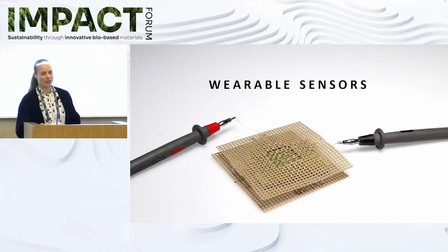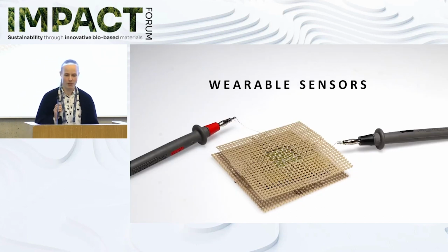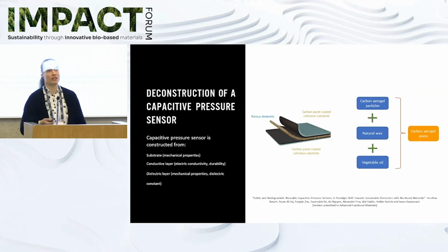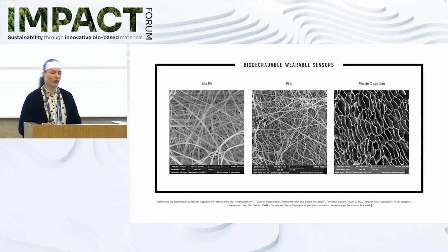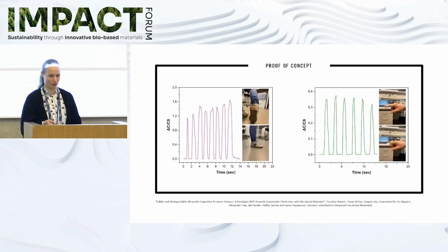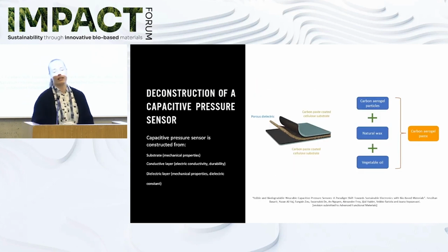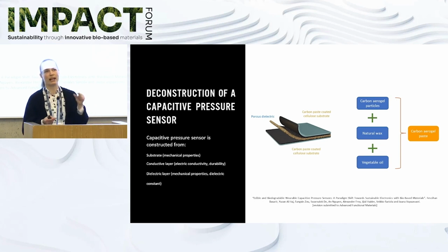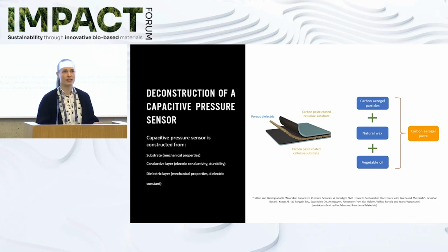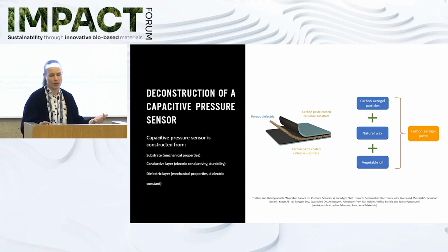Okay. Third case example, also very early stage research, wearable capacitive pressure sensors. Here, very much conceptually similar type of idea. We have here, again, a sandwich, which is again symmetric. So you need two substrates that are electrically conductive, and then a porous dielectric layer that goes in between them. Now, when you squeeze this type of device, the overall capacitance changes, which can then be converted into a pressure signal, and the exerted pressure can be measured.